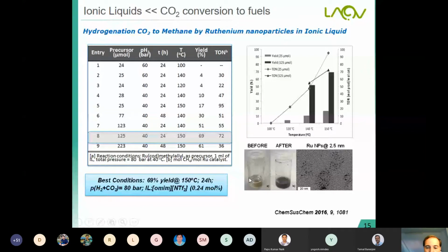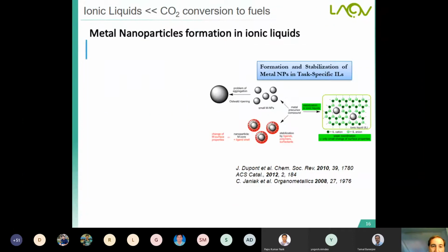And here you can see before, in the beginning of the reaction, and after the formation of the ruthenium nanoparticles in situ, and we proved by TEM the size of these ruthenium nanoparticles is around 2.5 nanometers. This is a very important point because in the literature, this is the first example for the formation of methane by hydrogenation of CO2 using only 150 degrees Celsius. Normally it requires higher temperatures and higher pressures. And the metal nanoparticle formation in ionic liquid is well known, the formation and stabilization.